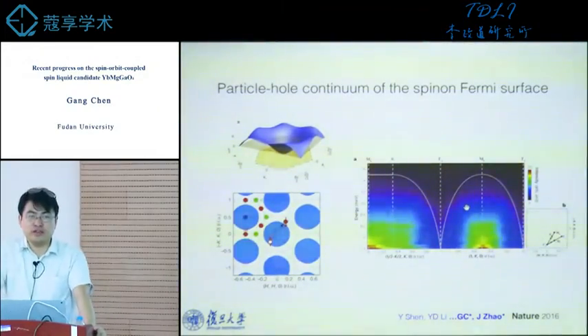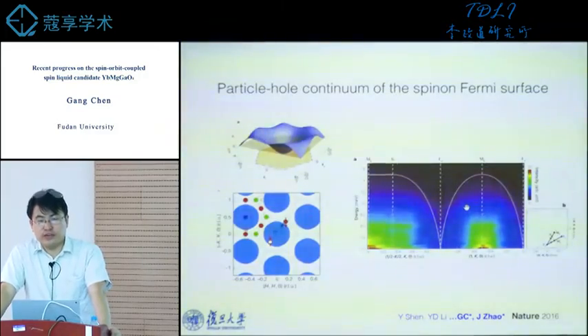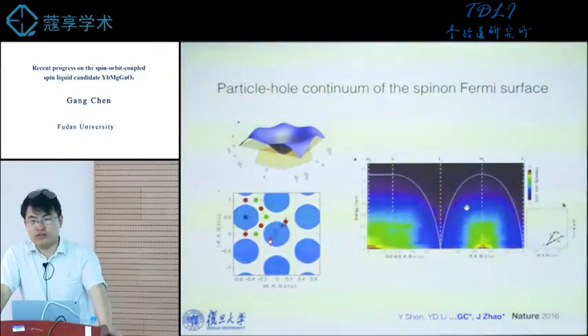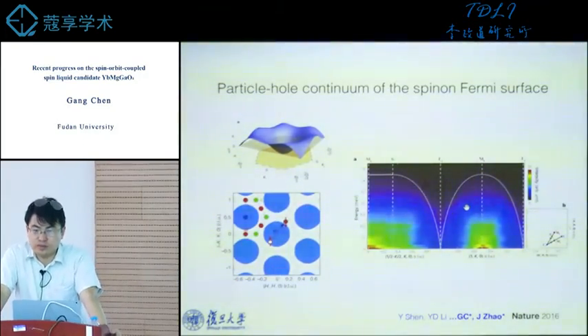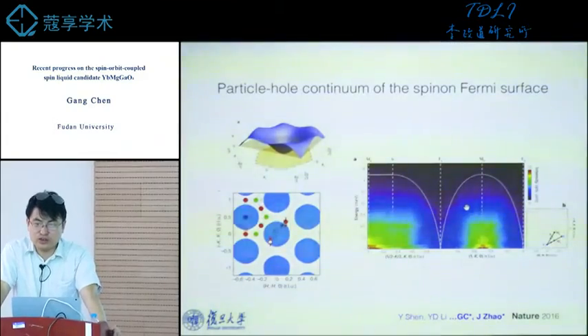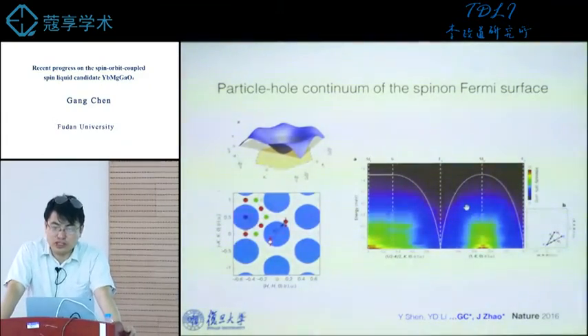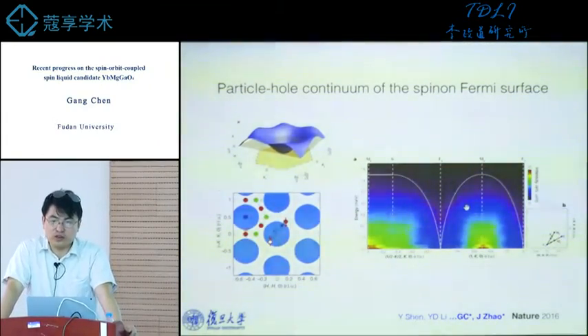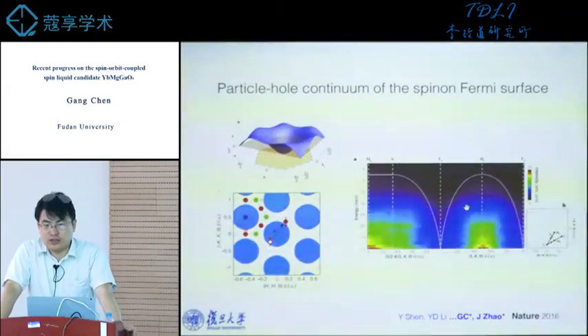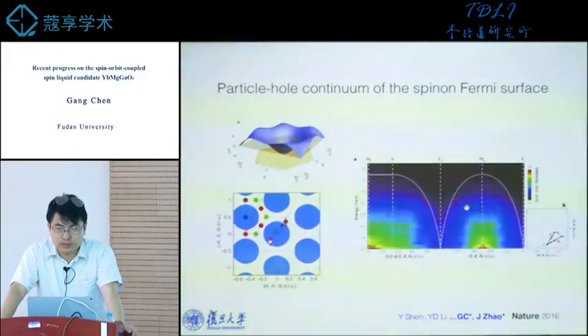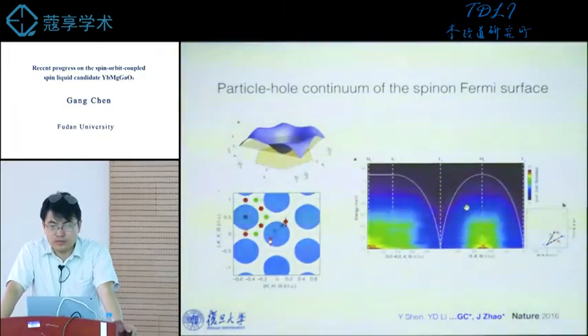It works very well. For very low energies, this is mean field theory. For very low energy, it doesn't really work because this ignores all these low energy gauge fluctuations, which are completely ignored. So at very low energies, the mean field theory is not going to be reliable. That's counterintuitive. Usually, mean field theory should work.